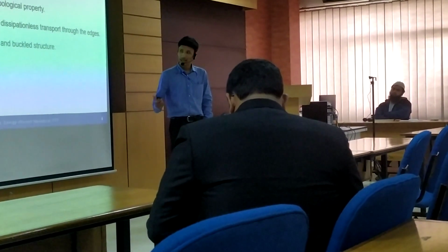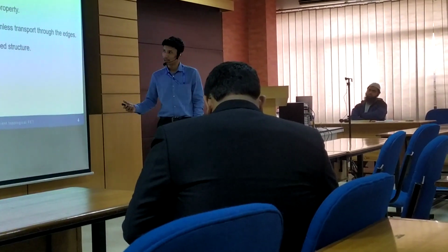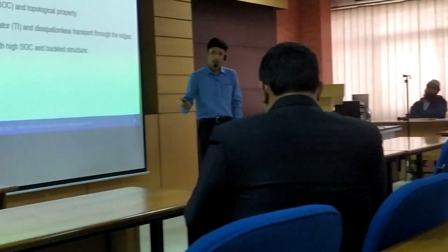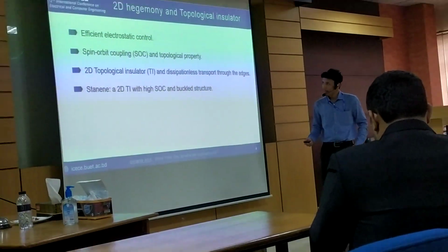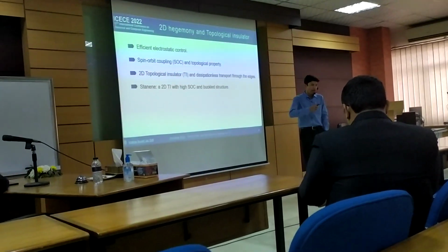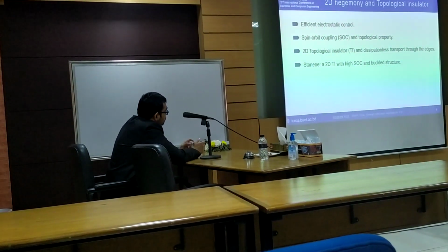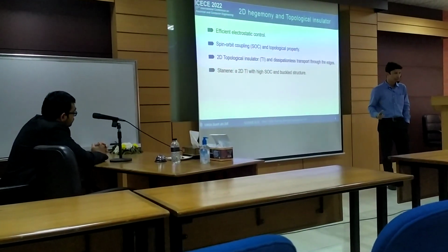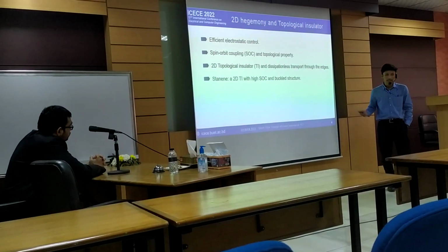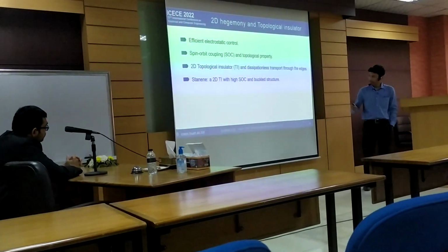Even germanium, silicon, and TMDs are not suitable, because of interface engineering challenges and higher impurity. At this moment, when we go to higher atomic number materials, an important quantum mechanical effect manifests: the spin-orbit coupling effect, which gives a new kind of quantum material property known as the topological insulator. For the 2D or quantum spin Hall insulator, this supports current through its edge, while the interior behaves like an insulator. That's why the name topological insulator comes.